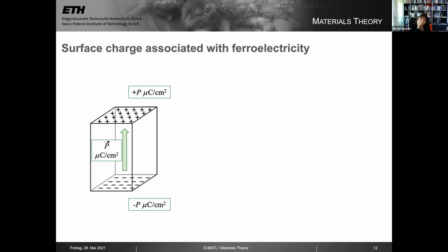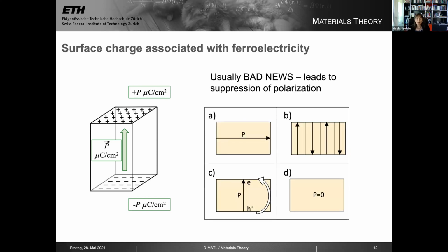If you want to have a stable ferroelectric device, let's say you want to store information in the direction of the polarization, having surface charge is very bad because you know that Gauss's theorem, this is electrostatically unstable. There's a discontinuity in the electrostatic potential, a diverging electric field. And so, particularly when you have a very thin film, so that these surface charges can be large relative to the volume and very close together, then this can be very detrimental to the behavior of a ferroelectric. And so it's usually bad news. People spend lifetimes trying to figure out how to compensate this surface charge. So it will somehow try to suppress the polarization.